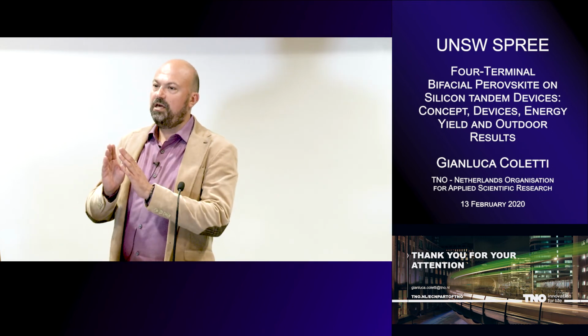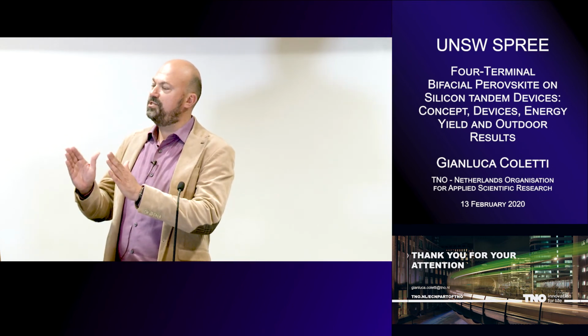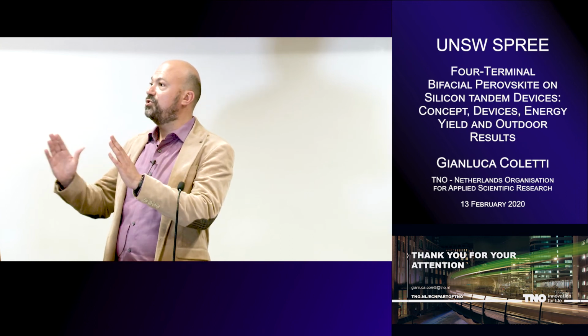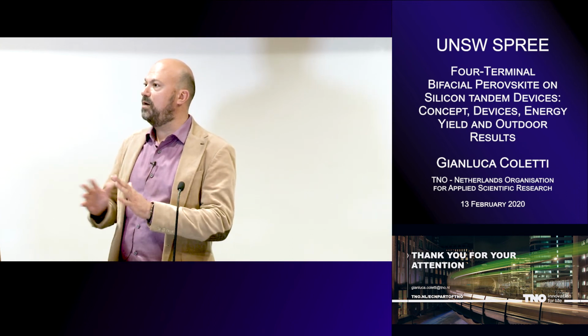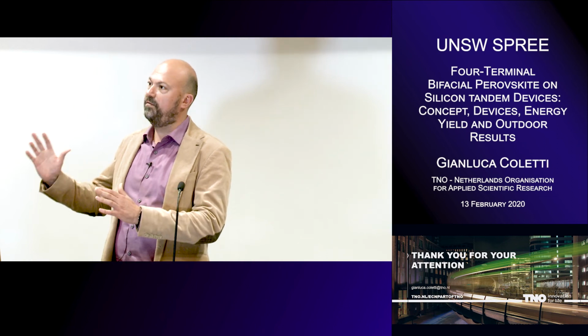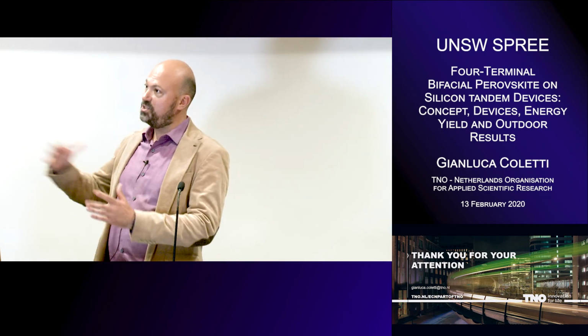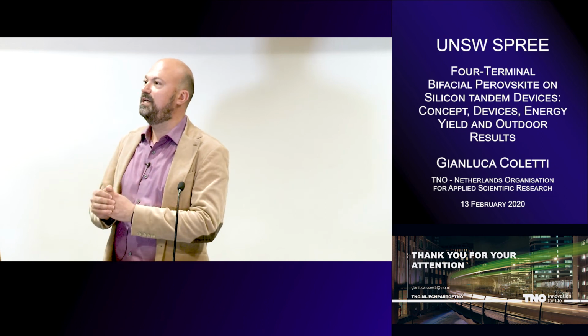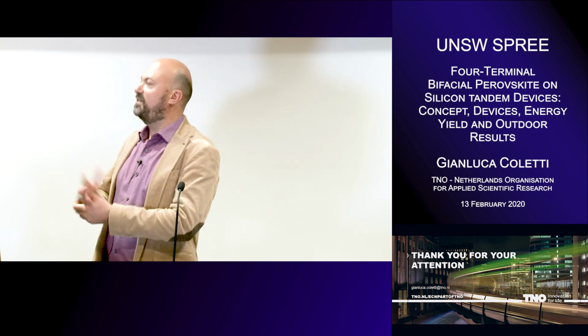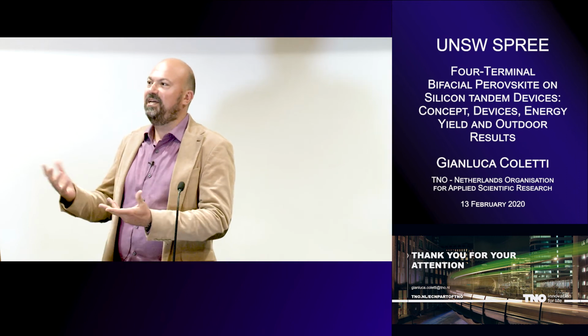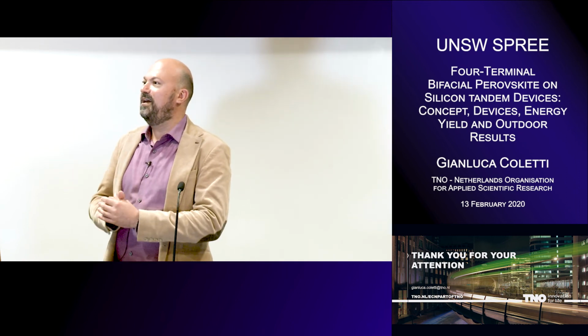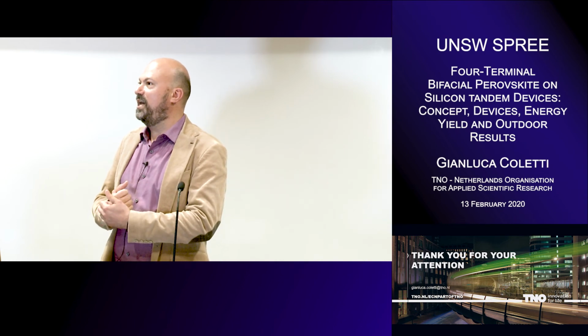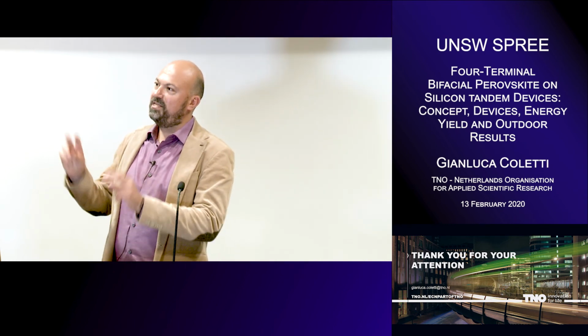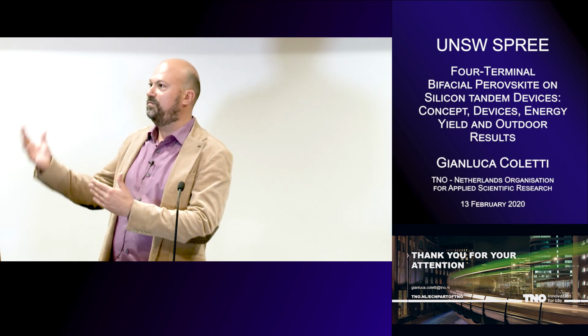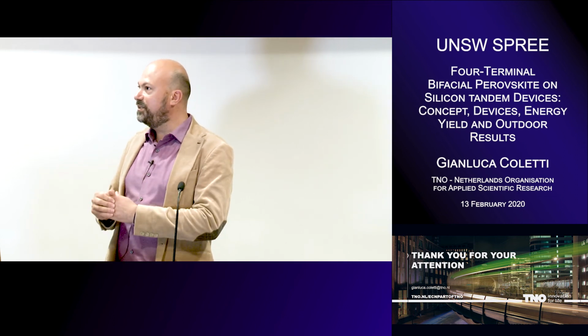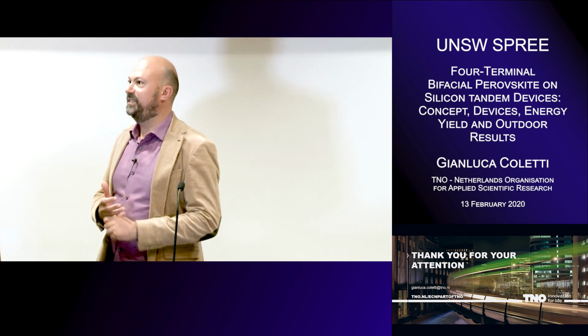No, so essentially the 1,000 hours that we registered outdoors is in the condition where we have the most variation. So we did it around the Dutch summer, where you can have really low irradiance and very high irradiance, because that's how you see most of the response. And that's where you should get most of the gain, but ideally you want to have at least 1 year, and we have seen that the results are pretty much in line. And actually when we measure in this, let's say, summer condition, you have a very good replica of the rest. If you measure only in the winter, it's not as representative. Yeah.